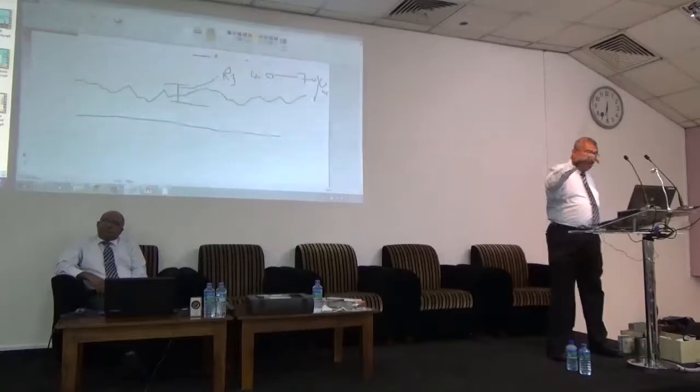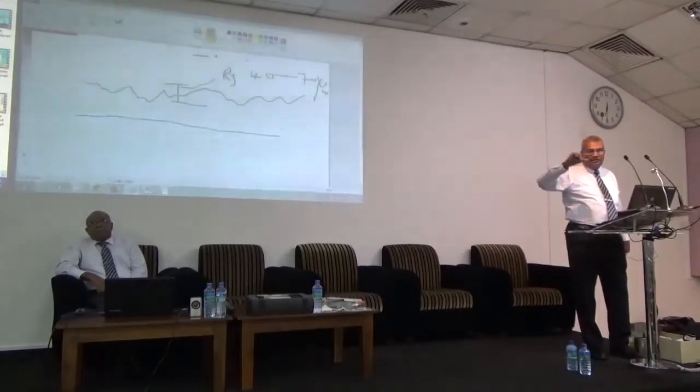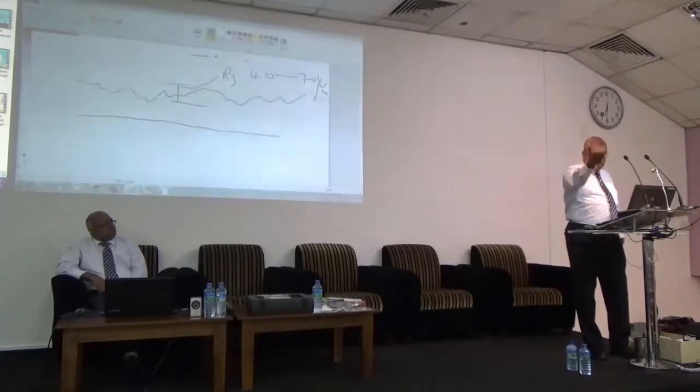Now, if you don't have that, it can also detach. That's what it means: if the profile has not been given properly, it can have a detaching effect. So now we saw that on the first or second day you use a grinder, the mill scale didn't go. The mill scale is very smooth. That also can detach, because when you have a smoother surface, you have a risk of detachment. Did I answer the question, sir?